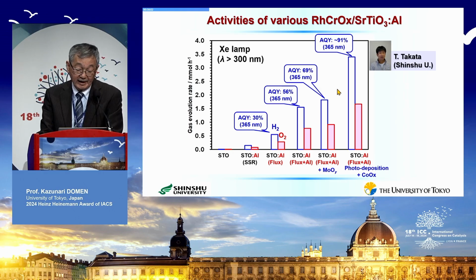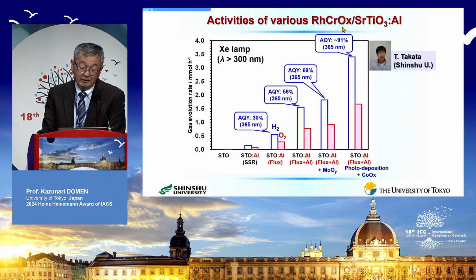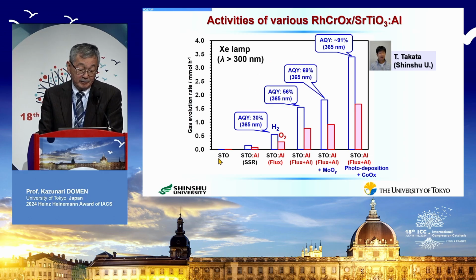These works were actually carried out after 2000. In this case, at first, we just modified it with rhodium and chromium mixed oxide as the hydrogen evolution co-catalyst. I'll come back to this co-catalyst later, but it is a very effective co-catalyst for hydrogen evolution. And we irradiated with a xenon lamp at wavelengths longer than 300 nanometers. When we used stoichiometric strontium titanate, the activity was almost nothing on this scale bar, in millimoles per hour. But actually, this photocatalyst can also evolve hydrogen and oxygen in a 2-to-1 ratio.